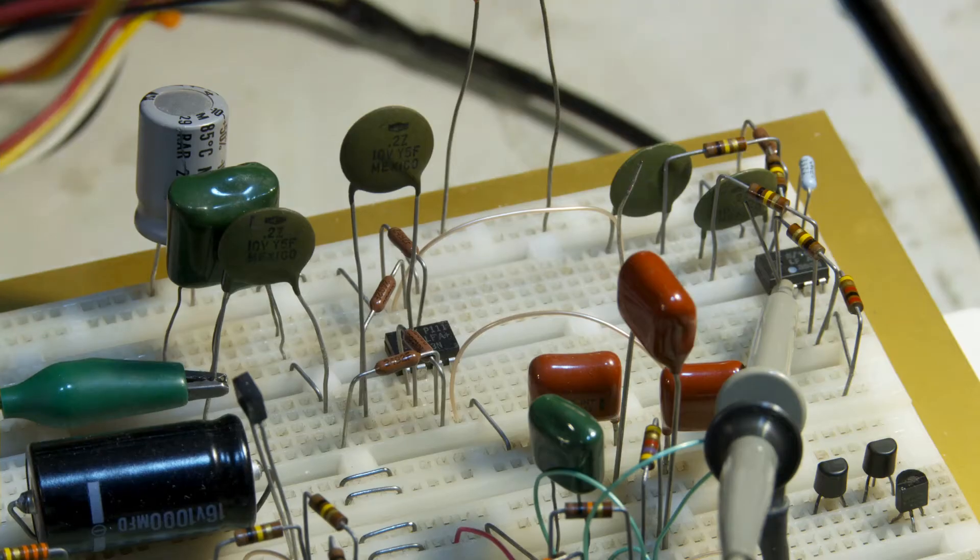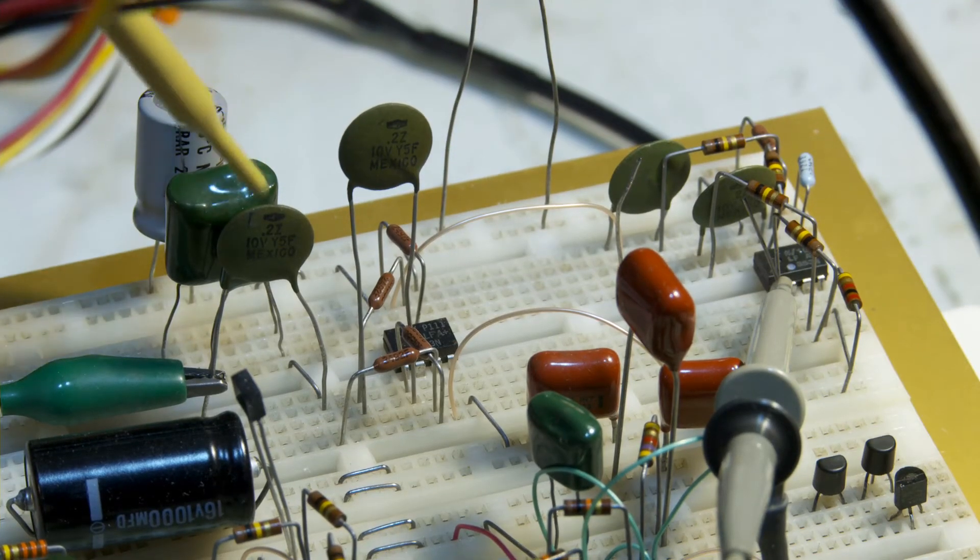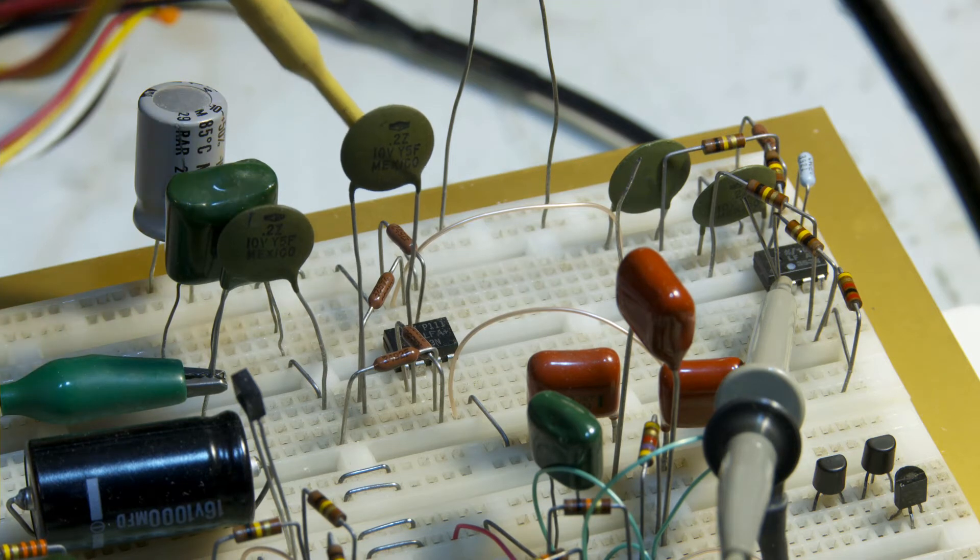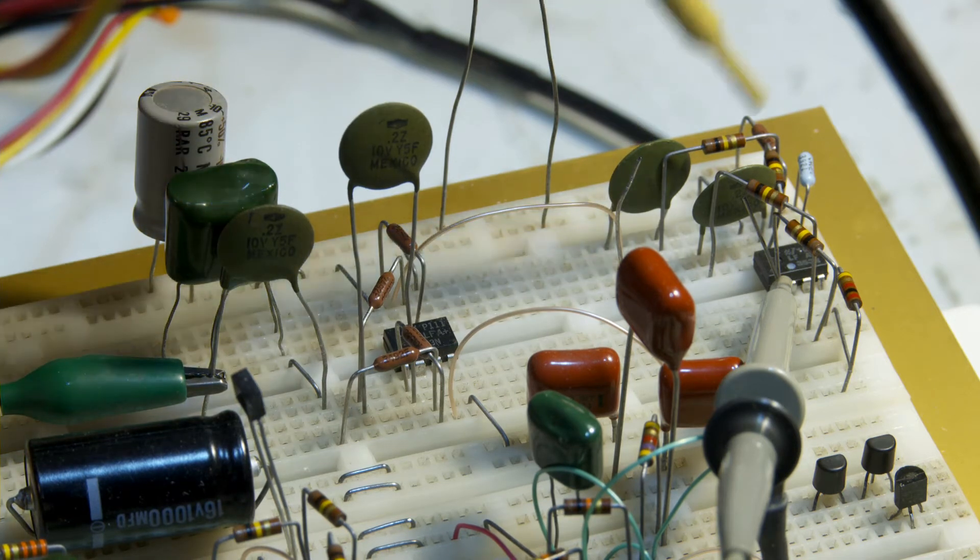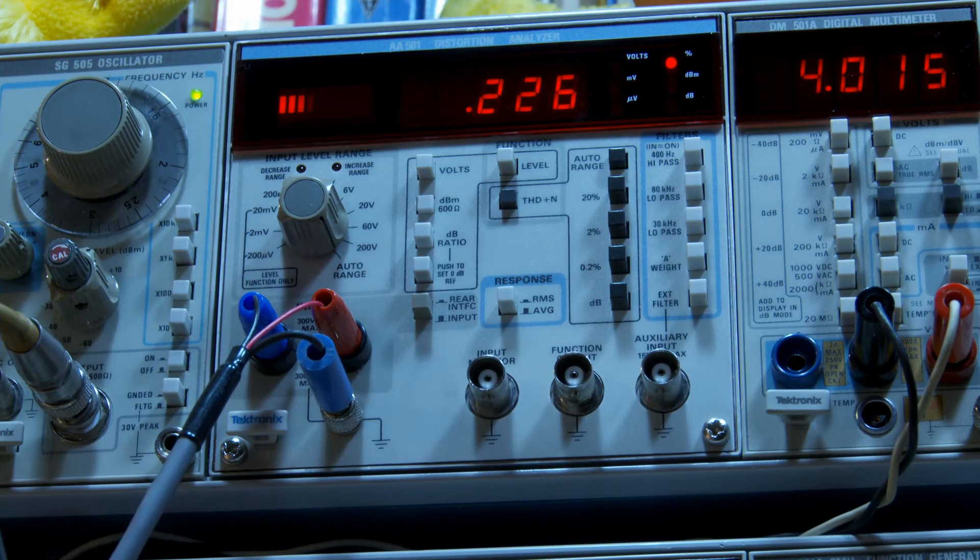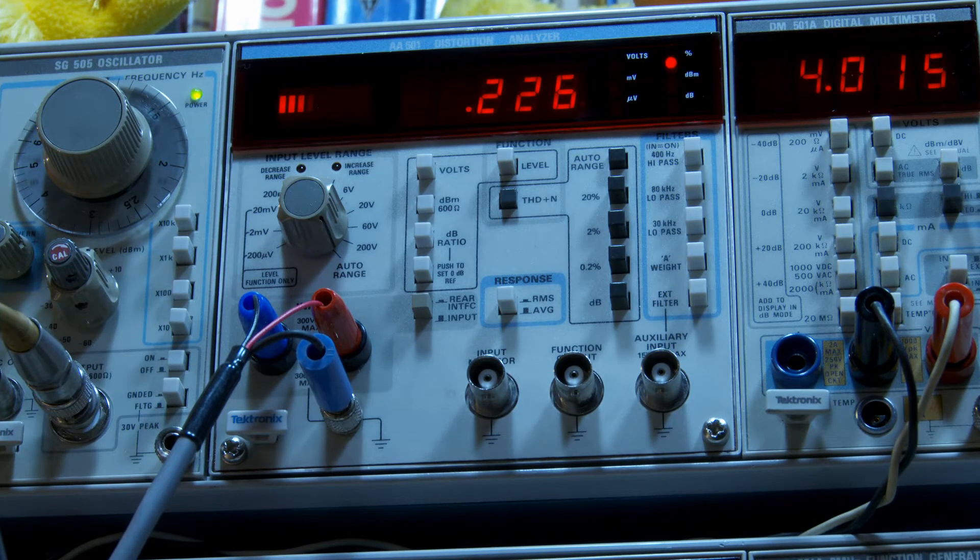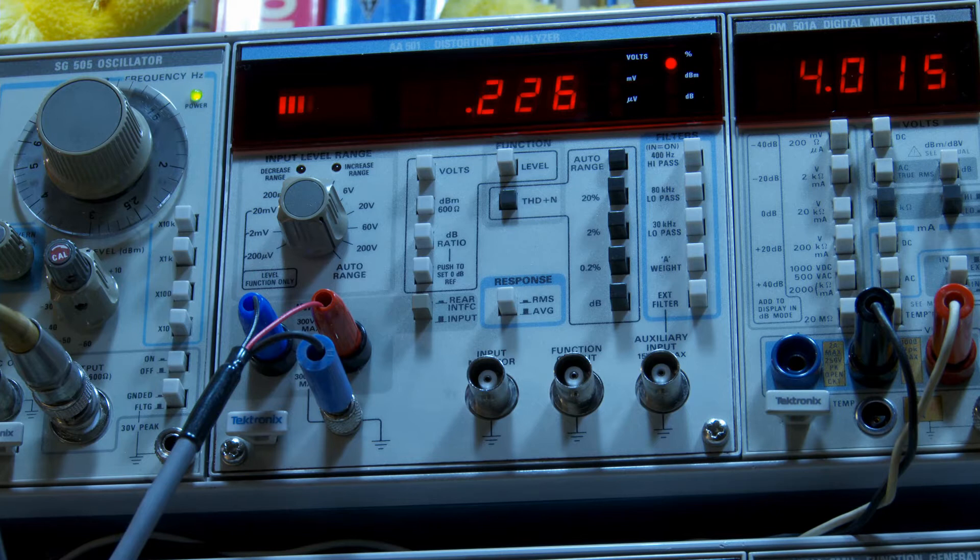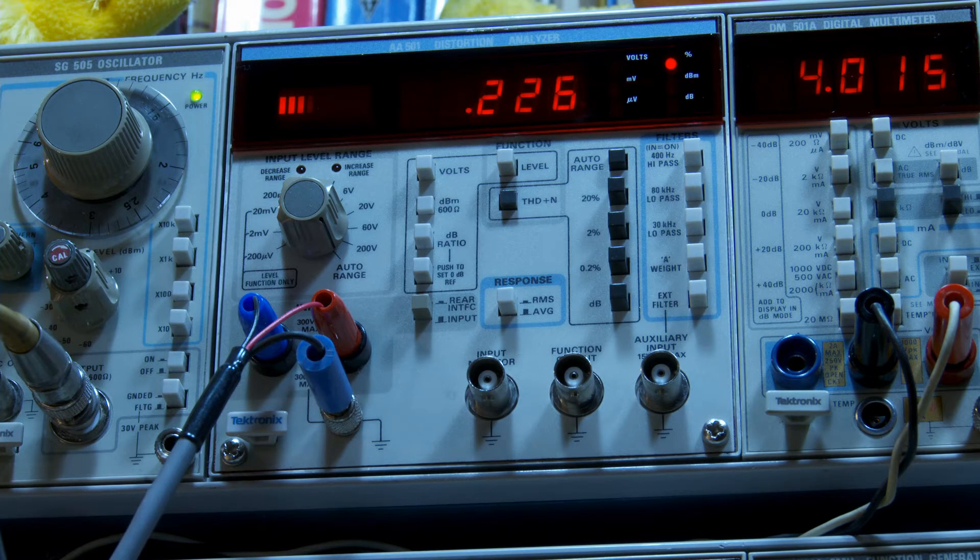Here is the test setup. We have a four-stage inverting op amp with four interstage coupling capacitors, ceramic of the Y5F composition. Our distortion is about a quarter percent with this circuit. Again, we're at 100 Hz.